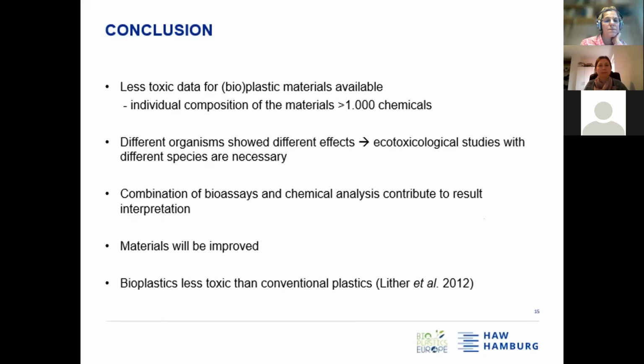For bioplastic and conventional plastic materials, less toxicity data are available. This is because every producer has an individual composition of the plastic material, and sometimes there are more than 1,000 different chemicals in one plastic material. So in this study, different organisms show different effects toward the plastic material. So it is necessary in ecotoxicological studies of plastic materials to use different species of test organisms. And in this study, we combined bioassays with chemical analysis by GCMS, and this combination contributed to the result interpretation. Like, for example, we found out that we had methyl naphthalene in one sample.